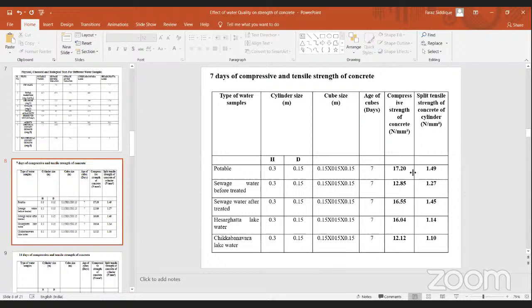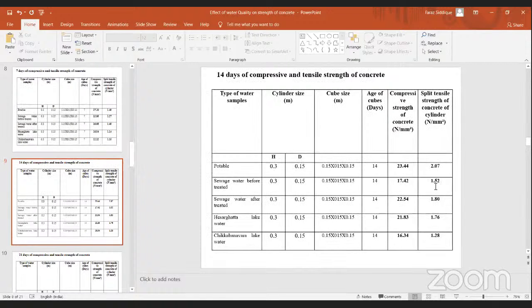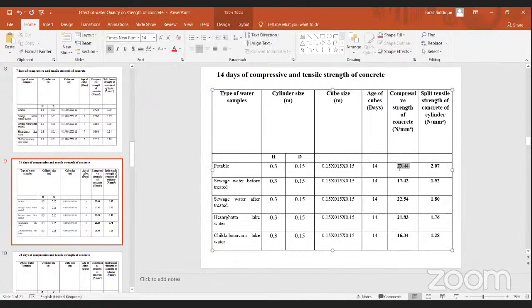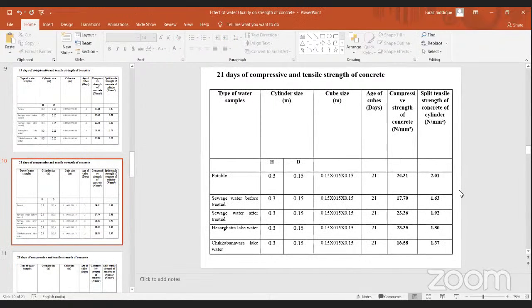For 7 days, we found that the potable water compressive strength was higher, and in the case of split tensile strength, also the same thing, the potable water had a higher split tensile strength of concrete. Then with respect to 14 days, we found that again potable water has the highest compressive strength, followed by the same with the split tensile strength of concrete. Then similarly, we have done it for 21 days and 28 days as well.